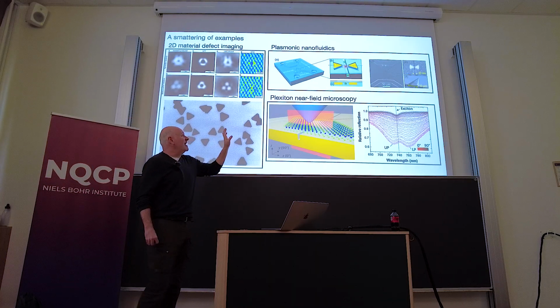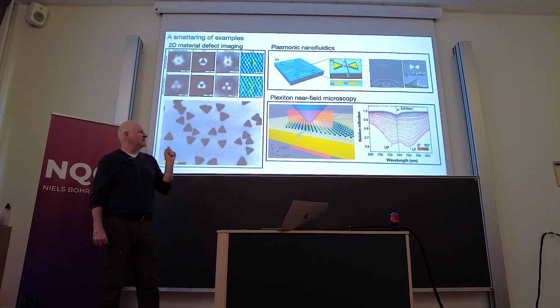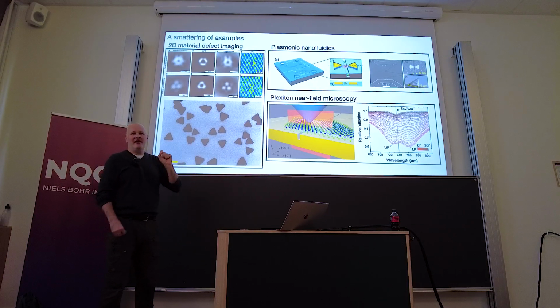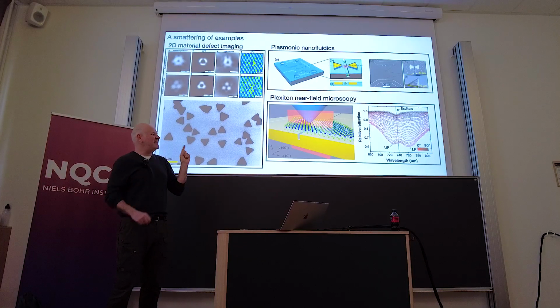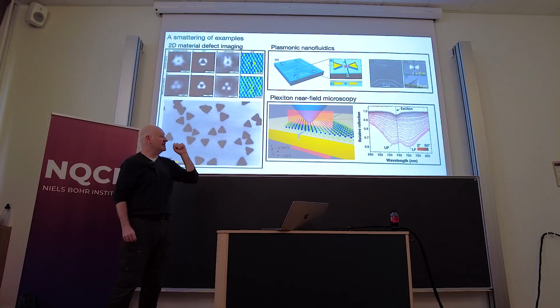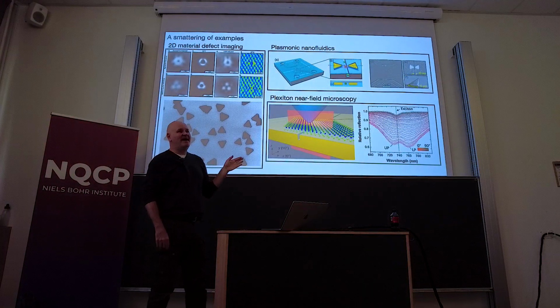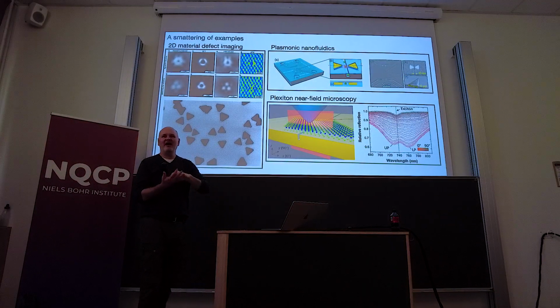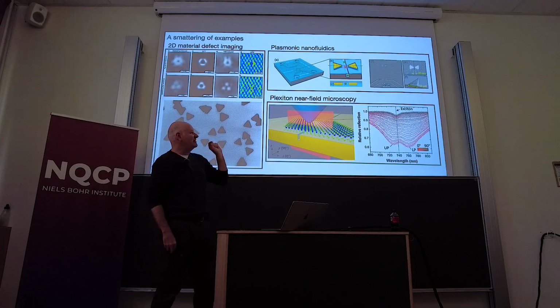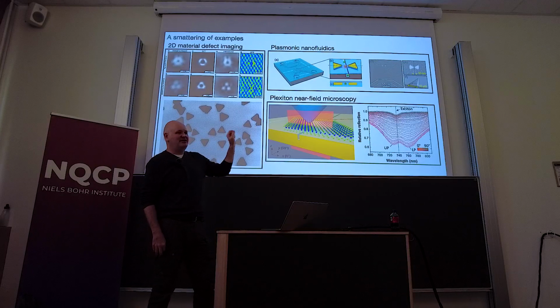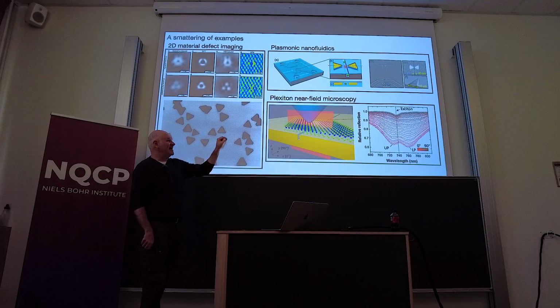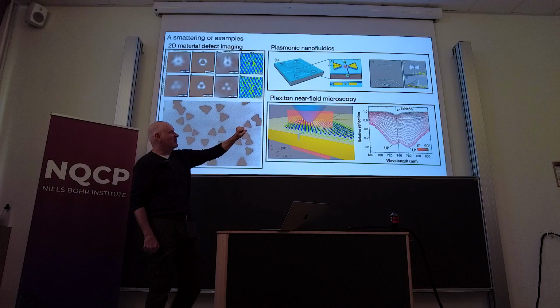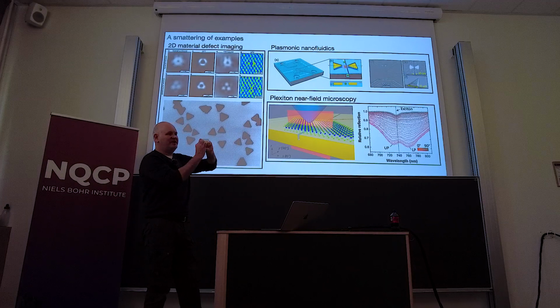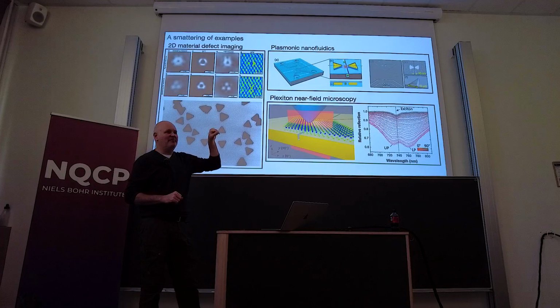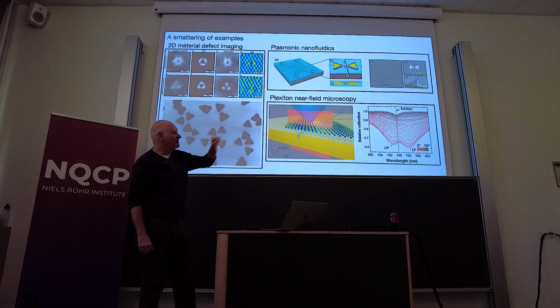We also had a big program on nanofluidics, where we fabricate nanoscopic, in this case 30 nanometer channels into, I think this is PDMS, I can't remember what this material is, but it's a resist material, and it's done by nanoimprint lithography. So you fabricate a very high resolution negative and press it into a resist, and you end up with a 30 nanometer channel. The especially tricky thing about these is not just a channel, but we also included plasmonic antennas into that channel. So if in the upper right hand corner you see this little bow tie thing, those are gold bow ties with a 30 nanometer gap to allow optical access, high field optical access into that channel.